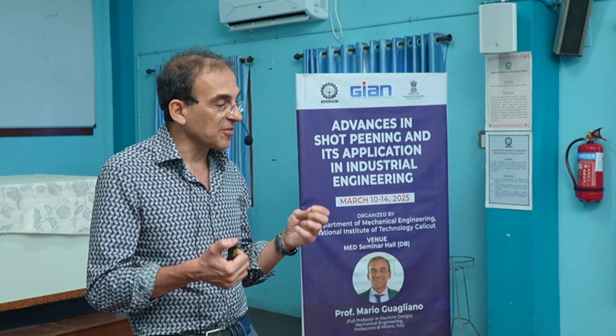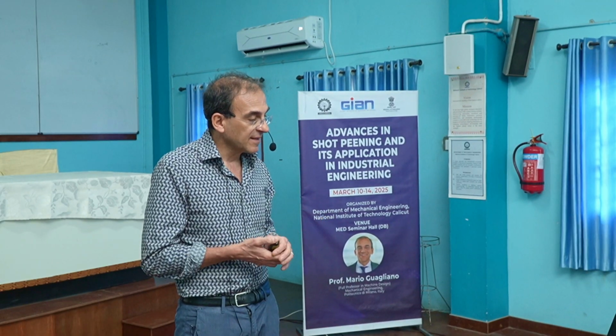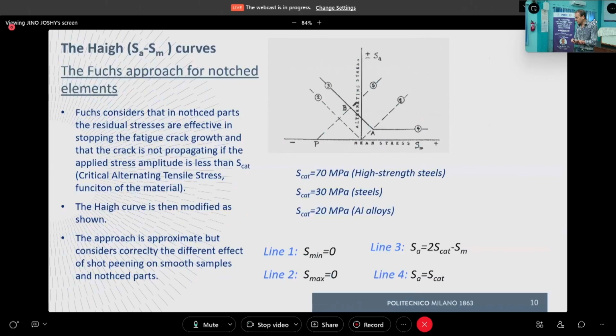And Fuchs applied this concept by modifying the Haigh diagram with, let's say, an approximate approach that is based somehow on fracture mechanics, but is not considering the fracture mechanics parameters, just the fracture mechanics idea. The Haigh diagram for the notched element is modified this way. He said that in each material a stress amplitude can be observed that defines the critical condition. The critical condition is defined by the so-called S-cat value, the critical alternating tensile stress, which is a function of the material.